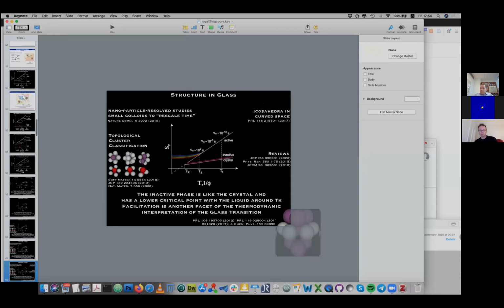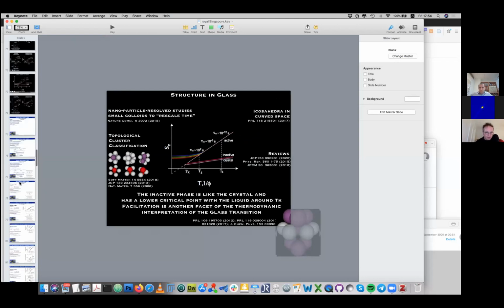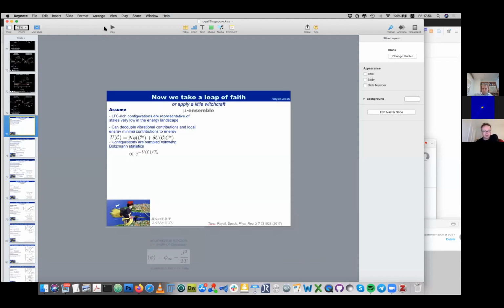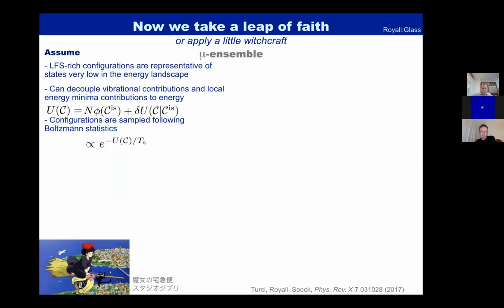What we sample is representative of equilibrium, but formally it's not in equilibrium. We use a biasing field to generate the samples. So we carry out this mu ensemble sampling. The mu ensemble generates data using equilibrium molecular dynamics, and then the trajectories are accepted or not accepted based on a Metropolis criterion for the number of local structures in it. So they are generated with just normal molecular dynamics.